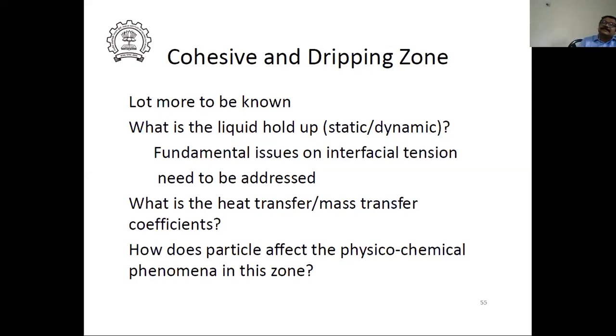But there is also a difficulty in pushing the furnace beyond a particular point, because the liquid is coming down and the gas is going up. As you increase the production, more and more liquid will be produced while the gas is going up. So it will offer resistance because more liquid is coming down, and then the pressure drop will increase. Then the operator will say the furnace is not taking the wind. Beyond a particular point, you start getting all kinds of problems. So this particular zone, with liquid and solid and gas going up, has an issue. That's why it's called the dripping zone. In modeling also, we had a lot of difficulty. We have to do a lot of tuning in this dripping zone, so we wanted to look at this zone in a more careful, fundamental manner.